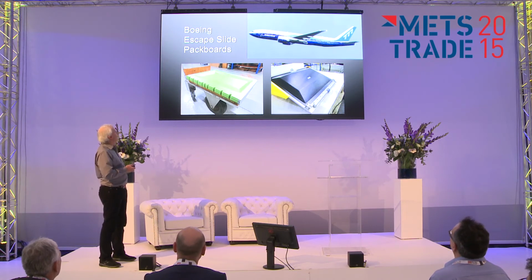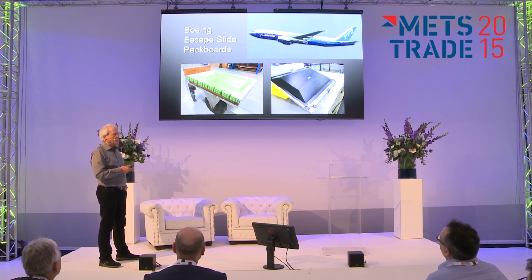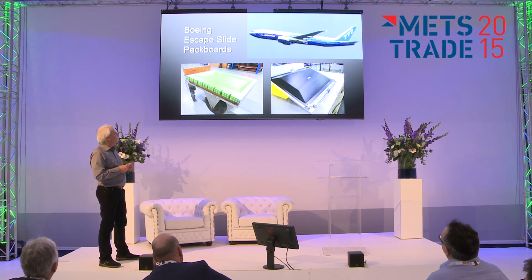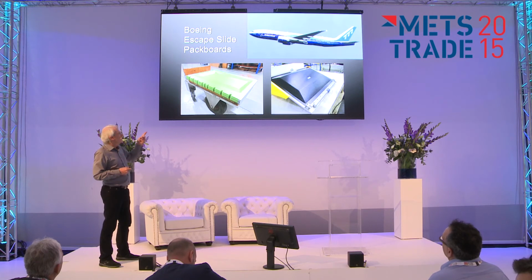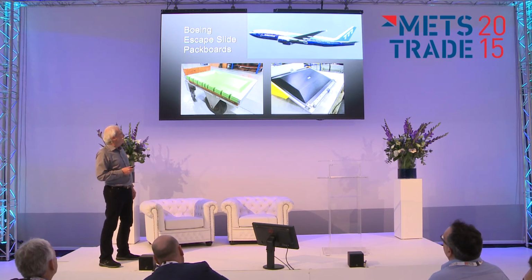We also make stuff for Boeing via Zodiac Aerospace, not related to the inflatable ribs, but basically we make this in a matched mold, and this is an example of parts that can be made in pretty high production levels. If we cook something in the autoclave, it's basically the autoclave table rolls in at about 3:30 in the afternoon, and the next morning you take it out. These are made in heated match molds, and one comes out every hour and a half.